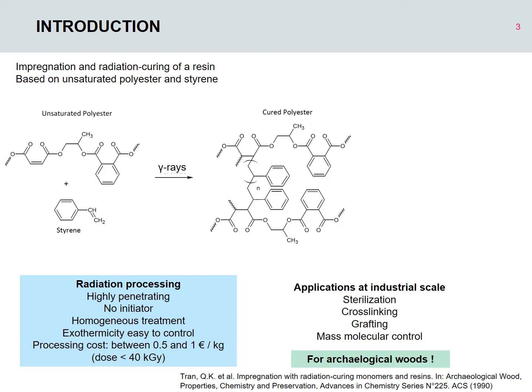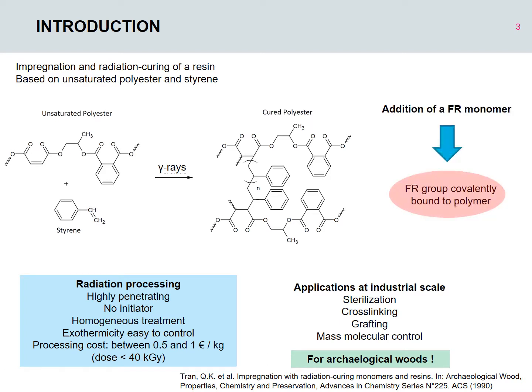Radiation processing is already available at industrial scale for sterilization, cross-linking, grafting, but also for protecting archaeological woods. And finally, if we add a monomer containing flame retardant groups into the resin, during curing, the flame retardant group will be covalently bound to the polymer, and so we can expect a durable treatment.